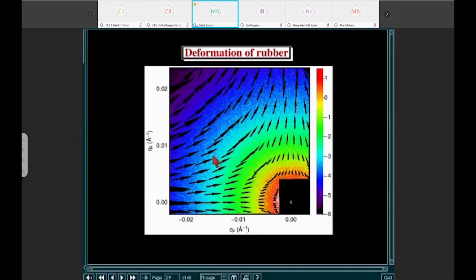Again, there's a lot more information in the speckle pattern. If you measured highly accurately the 3D speckle diffraction pattern of something, that's what CDI does. You can invert it and find the exact position of everything. Here, we just looked at how the speckles move across our diffraction pattern. And so what we're seeing in the black arrows here is how far the diffraction pattern moves as a function of time, in a stretched sample of rubber. You can see that they move in the horizontal, and they move out along the direction of stretching. And this is showing you the strain pattern associated with the relaxation in rubber. And so that's a whole new set of information that we can get beyond what happens just by measuring time constants.